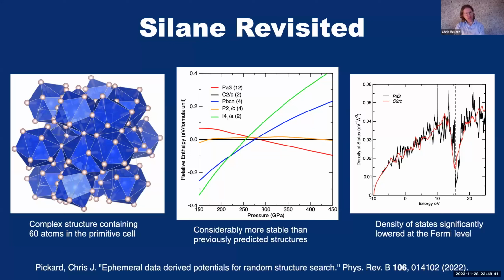And rather than looking at other people's and seeing if I could beat other people's structure predictions, I thought it was better to go back to my own early structure predictions on silane, right back to the start of random structure searching, and see what would happen if I did that with this new technology. And well, quite strikingly, and obviously you've seen that I published the paper, we found something new. So at high enough pressures, we found a completely new and very large complex structure with 60 atoms in the primitive unit cell, which was beyond conception in the early days of structure prediction, which actually was much more stable from an enthalpy point of view at higher pressures.